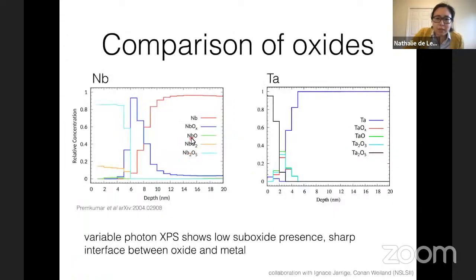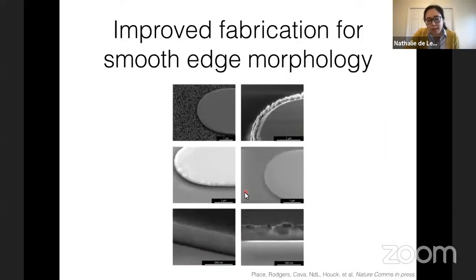And just to give you a direct comparison of these oxides, this is data that was taken by Conan Weiland and Ignace Jarrige at NSLS-II at Brookhaven. So they had this nice data set on niobium that they did in collaboration with Andrew's group, where you can see that you get all of these different suboxides, and you get a lot of effective oxygen diffusion into the metal. So it's really this very messy layer. Whereas in tantalum, you have this basically atomically sharp interface, to within the resolution of their technique, and very little suboxide contribution.